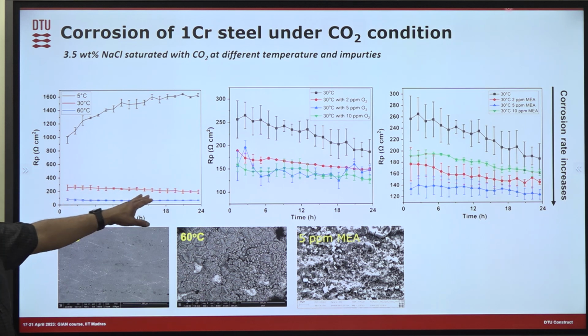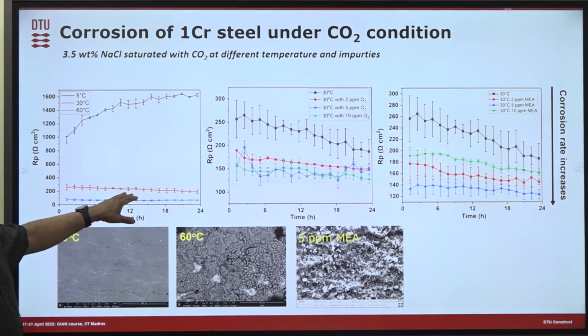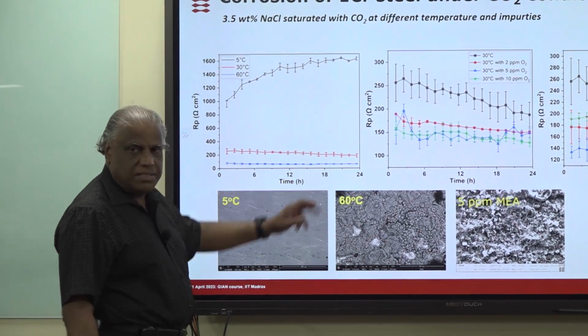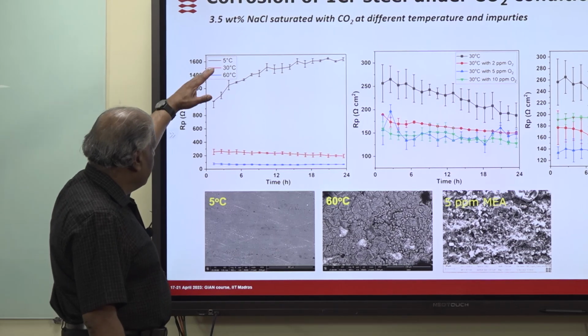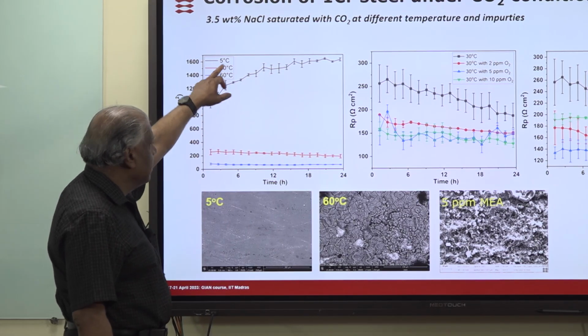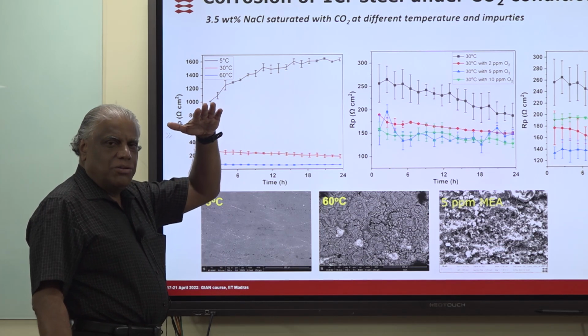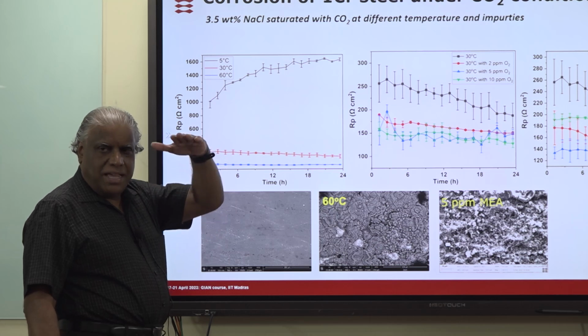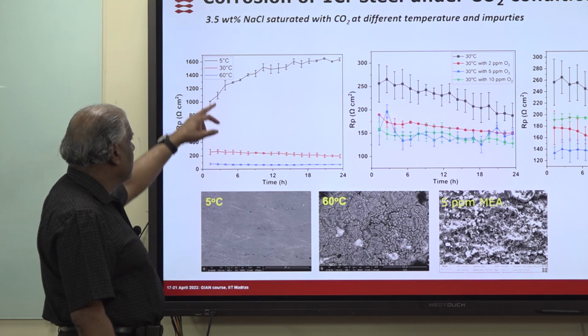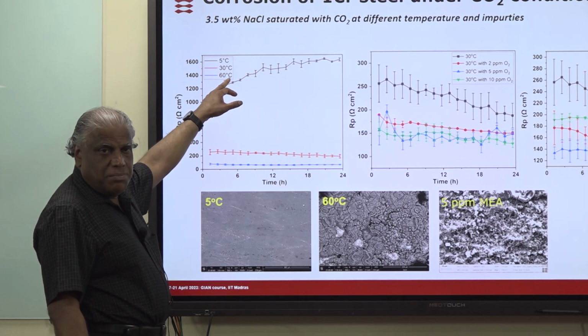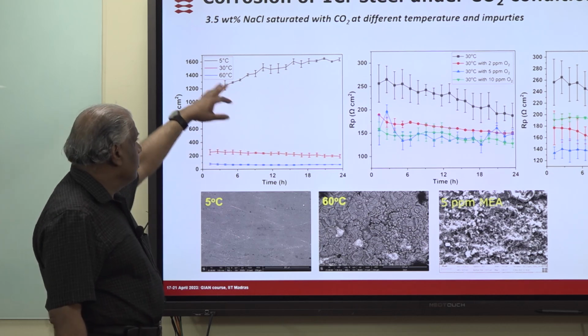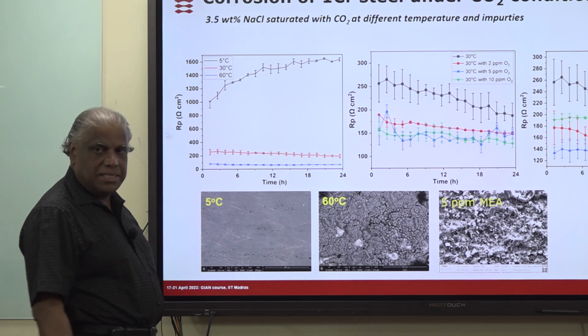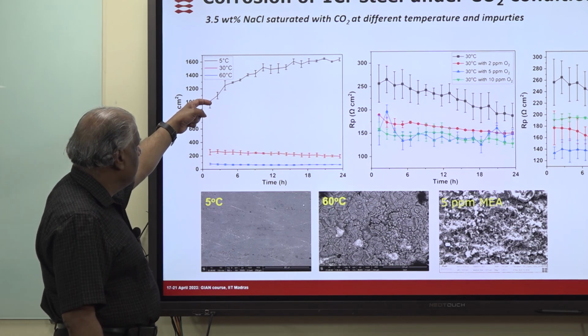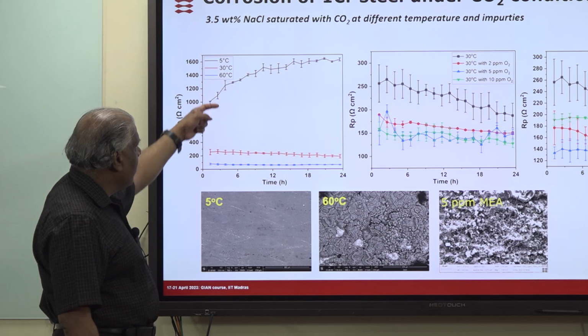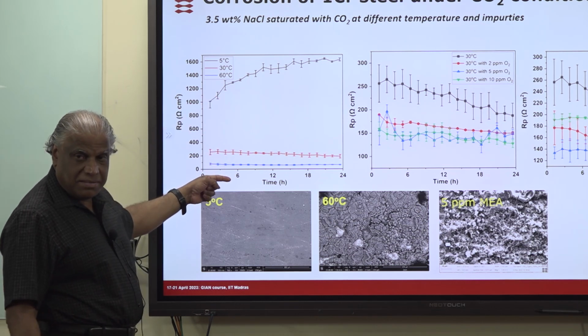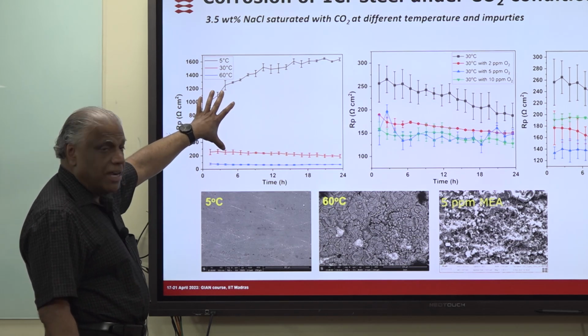I will just show you some experimental results. This is the LPR, the linear polarization experiments. With linear polarization experiments, we can study the corrosion rate versus time, and we are trying to study the temperature effect. You can see that 5 degrees is the kind of temperature we expect when the CO2 is injected at the top of the well, and the CO2 is going down. The temperature will come to 30 to 60 degrees centigrade, because the bottom part of the well will be much hotter, 60 degrees centigrade, and we are trying to see how the corrosion rate is changing with the temperature. You can see that there is a huge change in the LPR value from 5 to 30 degrees centigrade, but above that temperature the effect is less. So there is an increase in the corrosion rate within the 5 to 30 range.